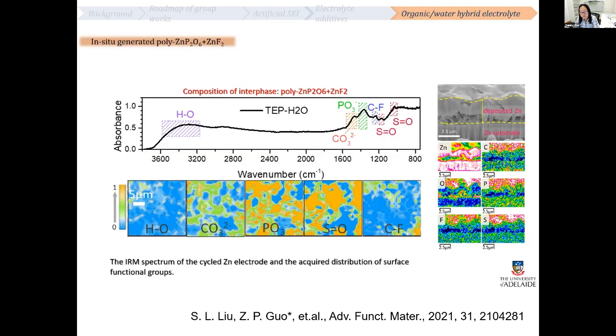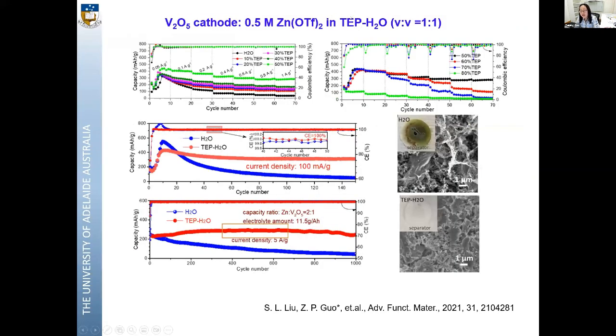From the detailed FTIR spectrum and also the functional group mapping, we found the TEP in the electrolyte, during battery charge-discharge, could form a composite SEI layer on the surface. It's polymeric zinc phosphate plus zinc fluoride. That's why we call it an organic-inorganic SEI, because this metal phosphate has a polymer-like structure. This SEI, because the TEP also has strong hydrogen bonding with water, reduces water reactivity. So you can see the separator is quite clean, meaning the vanadium pentoxide in this case does not dissolve as well.